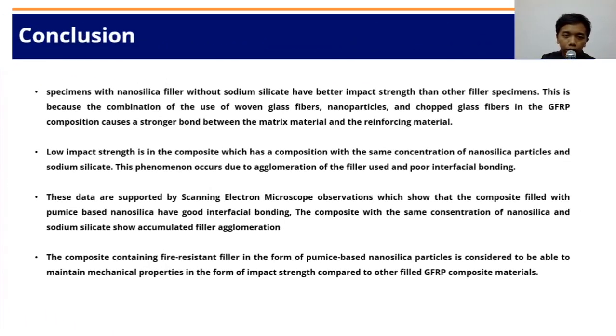And then the last part of this presentation is the conclusion about this research. From the research that has been done, it can be concluded that the impact test results show that the specimen with nanosilica filler without sodium silicate has better impact strength than the other filled specimens. This is because the combination of the use of woven glass fiber, nanoparticles, and chopped glass fiber in the GFRP composition causes a strong bond between the matrix material and the reinforcing material.